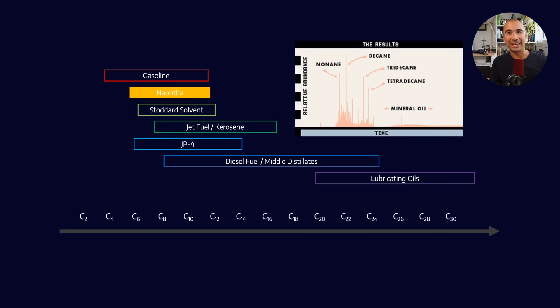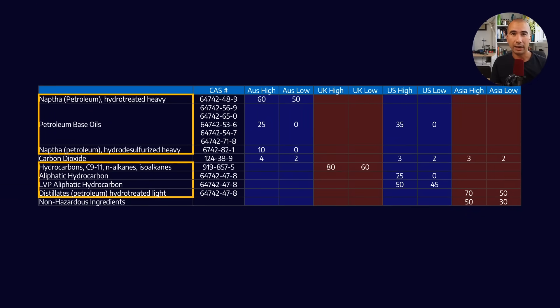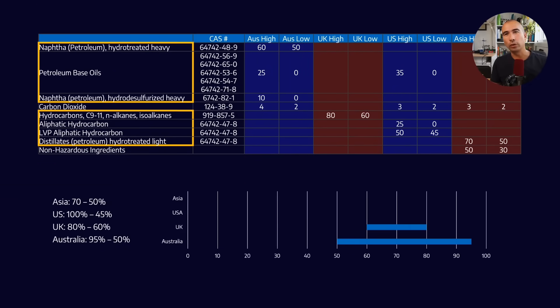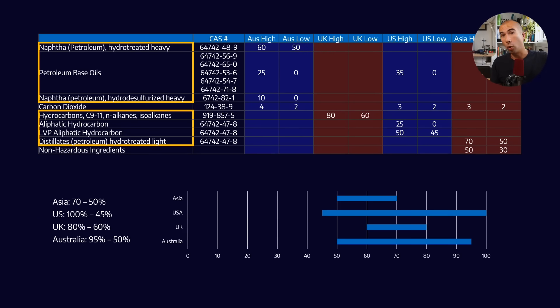Wired magazine actually did a breakdown of WD-40 and exactly what's contained within it. What they found was that the primary components are things like nonane and decane — that's C9 or C10 type alkanes. An alkane is a straight hydrocarbon. Going back to our table from the SDS data, what we can say is that anywhere between about 60 and 70% of the total WD-40 is these petroleum base oils in that C9 to C11 range.